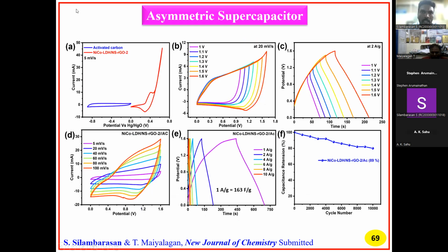Next, the asymmetric supercapacitor, a 2 electrode system with activated carbon and the nickel cobalt LDH composite with the NSRGO sample 2. We measured the CV at 5 millivolt per second for comparison. Next, figure B, the same scan rate with different potentials, measured by CV in the 2 electrode system. Then the same current density with different potentials for charge and discharge we measured in figure C.